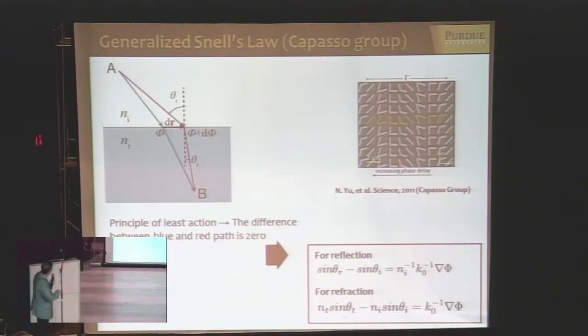When we look at the conventional Snell's law, it's dictated by photon momentum conservation. But if you introduce antennas along the interface, which shift the phase because of coupling to light, and if the antennas are different, the shift of phase is different. So eventually you get a gradient of phase along the interface, and as a result you introduce momentum, because gradient of phase means momentum in space. That allows you to send a beam in any direction you want, depending on the gradient you introduce. That modifies Snell's law.